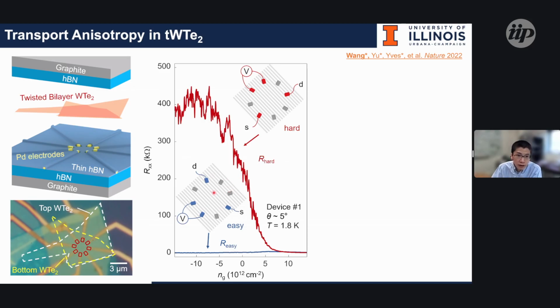You might have heard about the angle dependence from Leo's talk. This is a very similar geometry as Leo's presentation. So we try to measure along different orientations of the measurements. Along two orthogonal orientations, we can see the resistance goes extremely high and extremely low. Along one, we call it the easy orientation, the resistance almost goes to very low. But I want to note this is a scale problem, not superconductivity.